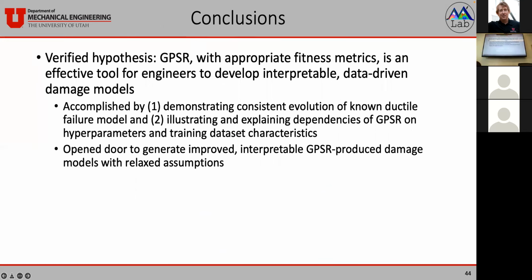So what are the conclusions? We were able to verify the hypothesis that using appropriate fitness metrics, GPSR is an effective tool for engineers to develop interpretable data-driven damage models. We accomplished this by, one, demonstrating that we could recover the Gurson model, which is a known ductile failure model. And two, we illustrated and explained the dependencies of GPSR on user-defined variables such as hyperparameters and training data set size. So what does this do? What have we added to the world? This opens the door to generate improved interpretable GPSR produced damage models by relaxing assumptions. As we discussed very early on in the presentation, a lot of those analytical models have assumptions underlying them, and this results in poor accuracy.